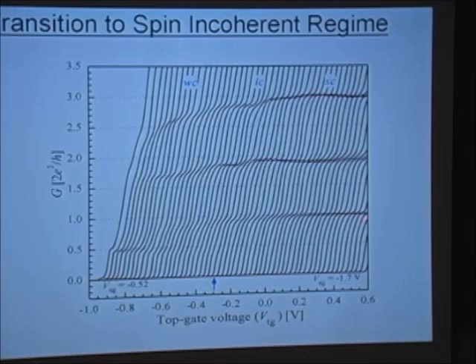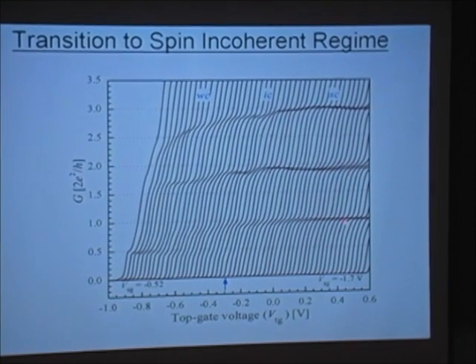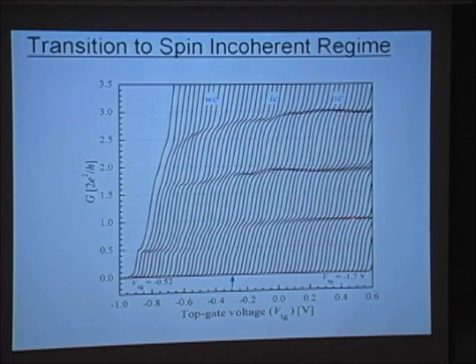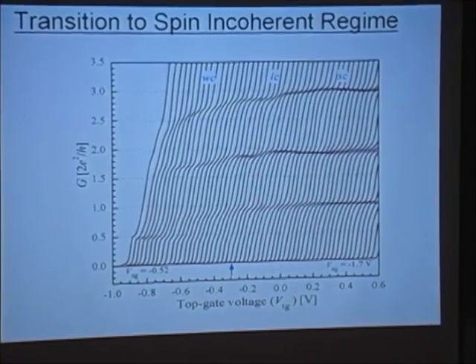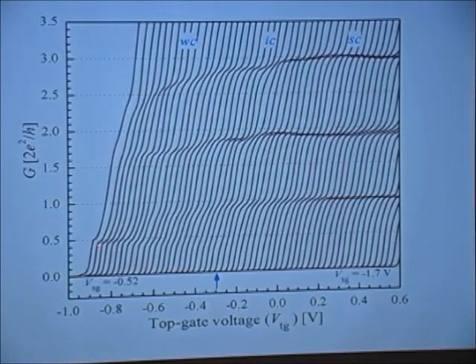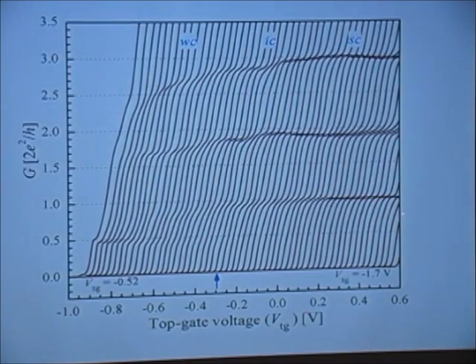And this is an example. Remember before, the quantized resistance or conductance, all it does really is it counts levels. Now, what we're going to do here is really reduce the density of electrons considerably until we get into this regime. So here we see the normal effect, quantization in units of 2e squared upon h, 1, 2, etc. And you'll notice it disappears, and it reappears there at e squared upon h, 0.5 times 2. Now, what that means is the basic unit of quantization is e squared upon h, but here we have 2e squared upon h, because by having a spin, we can put 2 electrons into the same momentum state. That's fairly standard work.